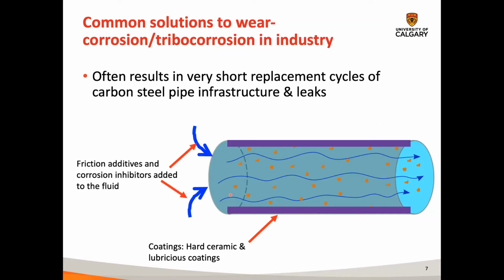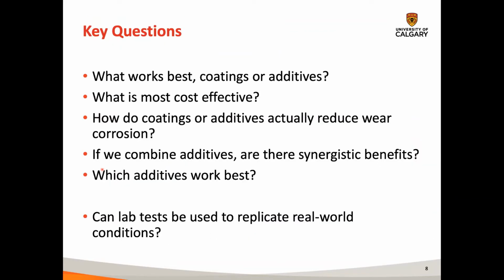And then what CalFrac is doing is they put additives, or I should have said corrosion additives. So we're having a fight over some with the reviewers over some papers we submitted. So they add friction or corrosion additives to reduce the friction between the steel pipe walls and the debris, and then also corrosion inhibitors to reduce the rate of corrosion of the pipeline steel. And then the last thing that we're playing around with in the lab here is you could use an epoxy coating, which is pretty common in, I think, corrosion science. And so we're looking at how the epoxy coatings might change friction as well between these rock particles in the wall. So the key questions that we're trying to answer in these projects is what works best, coatings or additives.